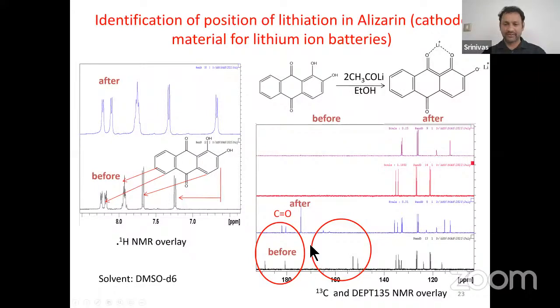But if you see that from before and after, from the 140 to 160 region, you see complete displacement in the peaks. Whereas in 180 to 200, only one peak is much displaced, whereas the other peak is not much displaced. That means there is not much lithiation happening here. The lithiation that is happening is to this 2OH and to this carbonyl, by which you can understand the mechanism and write a mechanism. So lithiation is happening here as well as it is forming a 6-member ring here, but it is not attacking here.